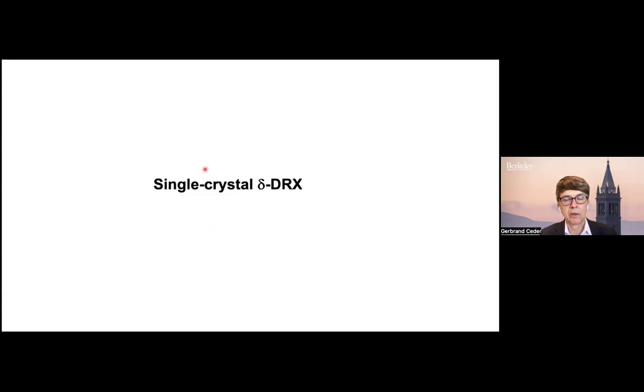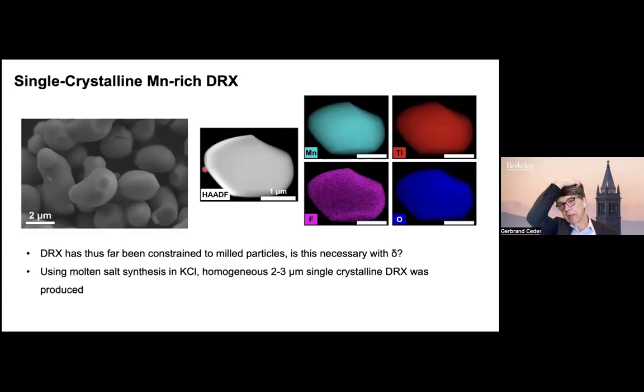So the improvement that delta DRX gives you in rate capability has allowed the use of larger single crystal DRX. So again, in the past, a lot of this early work I showed you in the talk were materials that were heavily milled. So the single crystallite size would be like 1 to 200 nanometer. And that's because of the often somewhat poor rate capability. So now when we can increase the rate capability, you can actually use larger single crystals. So here's sort of 2 to 3 micron single crystals. They're very homogeneous. These were made by molten salt synthesis, but just like people are trying to make single crystal NMC with direct salt state synthesis, we're kind of trying to do the same.